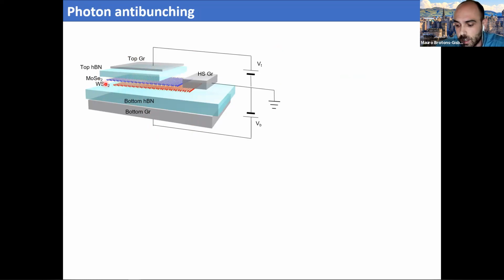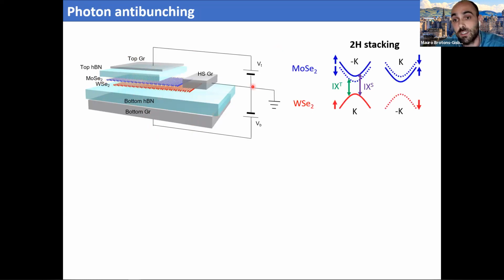So for this heterostructure, we chose to stack the two layers with 60 degrees stacking. This is what's known as 2H stacking. And this basically means that we have the K valleys of one material aligned with the minus K valleys of the other material, and vice versa. If you think about the possible optical transitions for this configuration, we have two possibilities. The lowest is an interlayer exciton with a triplet spin configuration that involves the lowest conduction band. And then we have an interlayer exciton with a spin singlet configuration that involves this higher energy conduction band. So again, we fabricated the sample, we cooled it down to 4 Kelvin, and we measured photoluminescence.